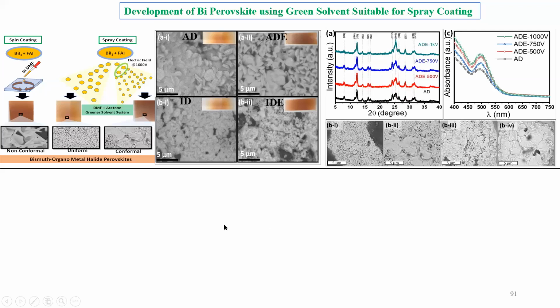So the same type of material, and we got better film. These are some materials where I took different solvents to see the morphology by spray coating, and I found that at a particular concentration and by choosing a better solvent, I get a conformal film, which is not porous. These other films have some porous structure. Now this is a conformal film, so electron transport will be better,